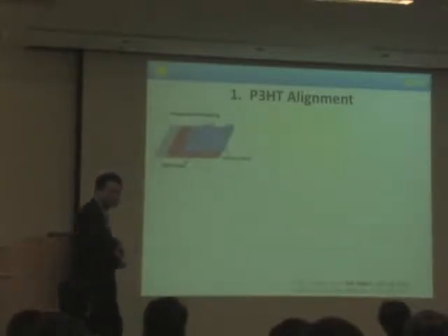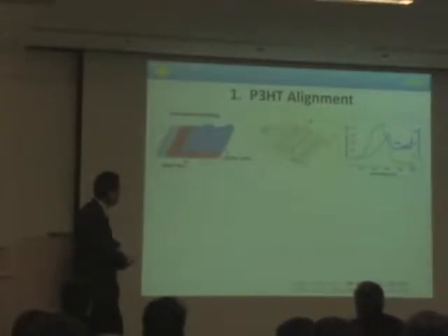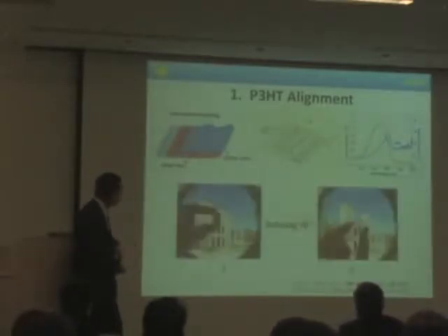You can see the dichroic ratio we achieve is about 16. It's not perfect, it's not 80, but 15 or 16 is not bad either. So we're able to polarize the film. You can see this is a piece of polarizer, and this is parallel to the polarizer, and this is perpendicular to the polarizer, one way or the other. In fact, if you look at the latest issue of Science magazine, you can see this article with these pictures there. This is the famous UCLA Royce Hall.